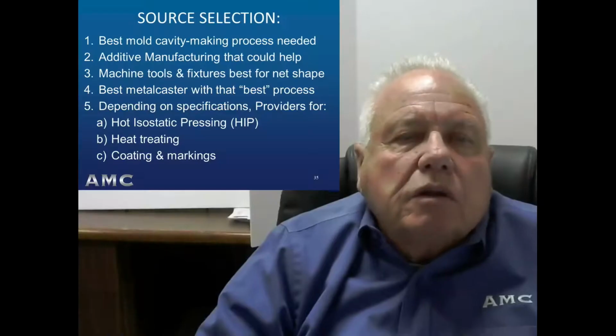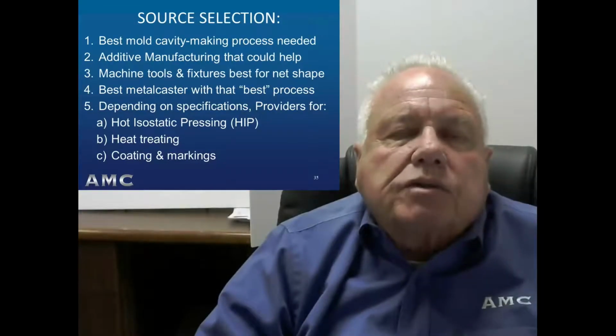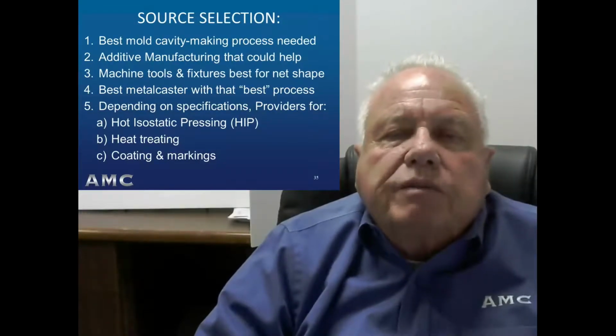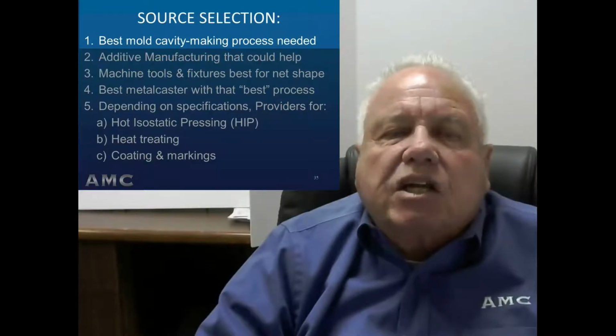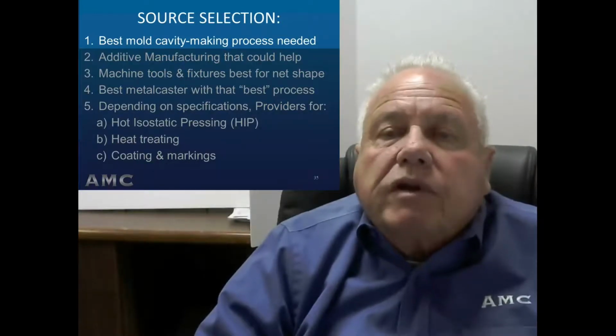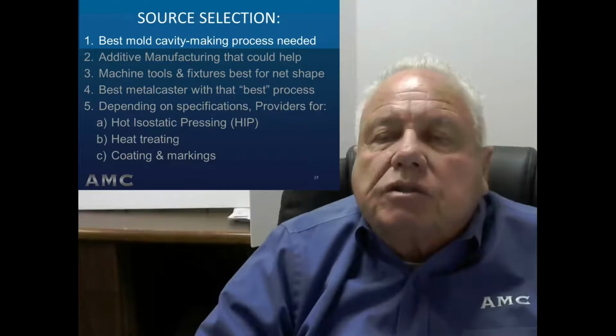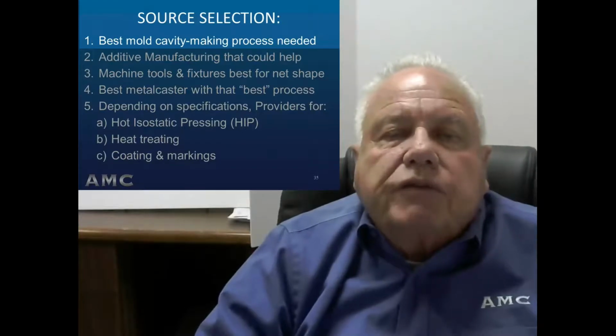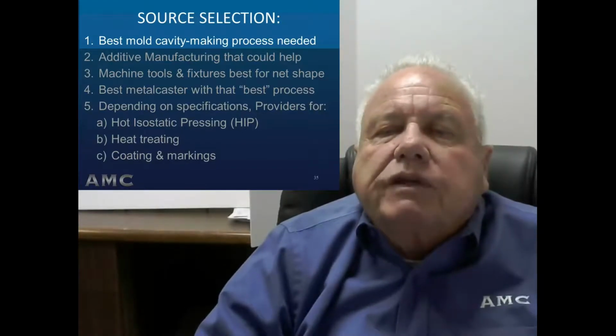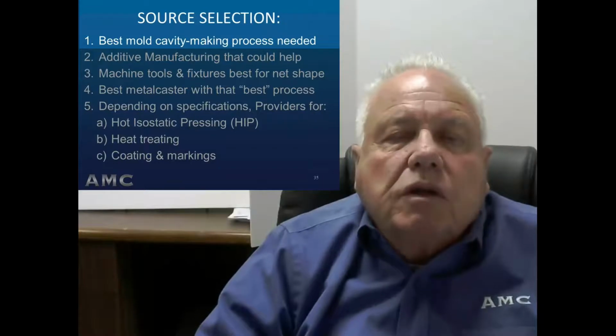In my turnkey role, being responsible for delivery of finished castings, here's a list of what I do in collaboration with my metal caster, machine shop, heat treater, and coater partners. Initially, during the bidding process, I make sure selection is based on the requirements of the finished casting, including the best mold cavity making processes based on the dimensional, surface finish, and solidification integrity required in the finished casting specifications.